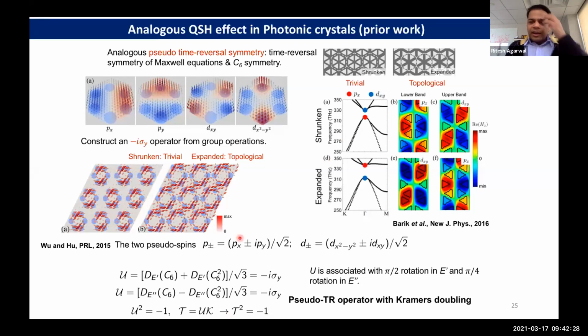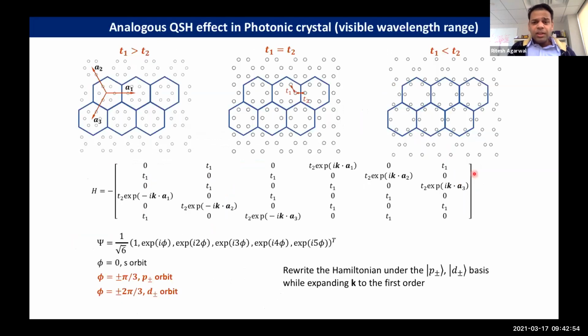So this was the idea, and then a few years back, Mohammad Hafezi's group came up with a better experimental realization of this system. They realized that instead of making these circular holes, where you cannot create a very nice band gap and light is not very nicely confined, you make these triangular holes, but following the honeycomb symmetry. One can realize these things